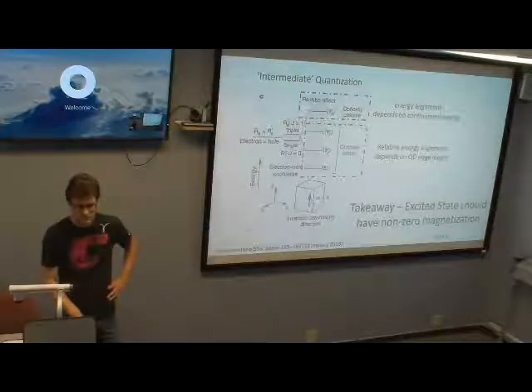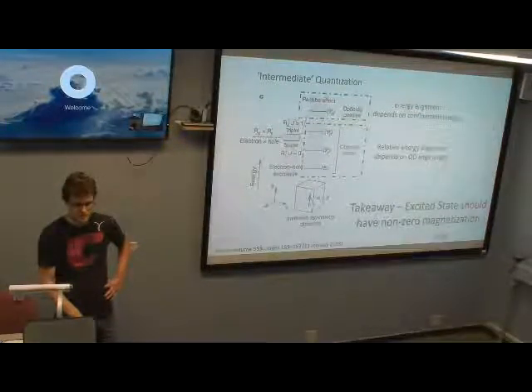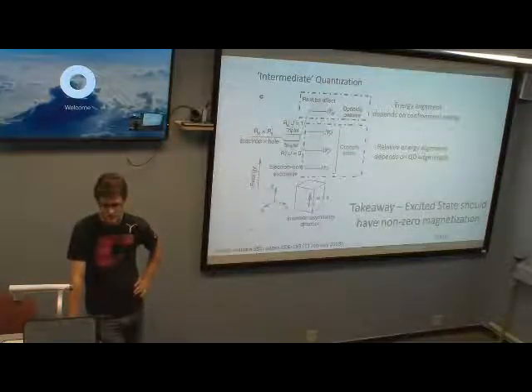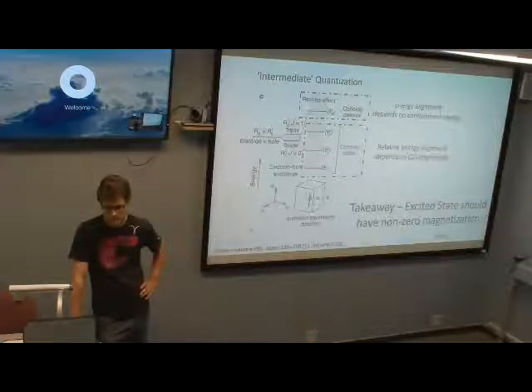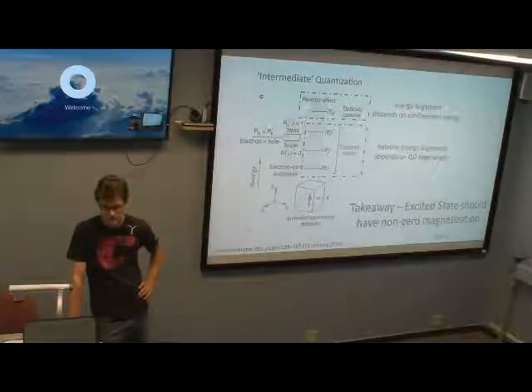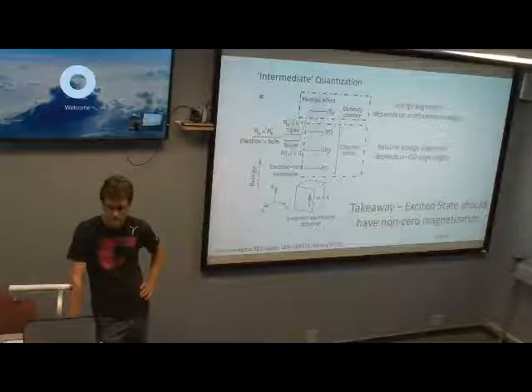So you have a singlet, like your alpha beta, if you're not including spin orbit coupling. So then your singlet transitions, your low state is dark, or is optically inactive. So for the spin restricted calculations, you can look at the triplets in the spin-restricted calculations, right? I guess the lowest... get the idea which of them would correspond to these conclusions, whether your singlets will have less optically active transitions compared to the triplet state. Because you can just look where is your alpha and beta for creating a triplet state.